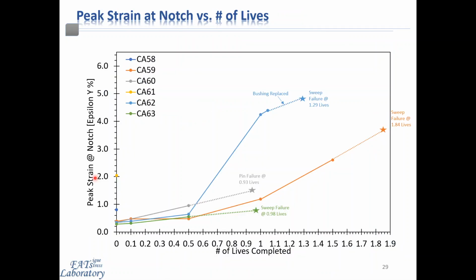So now the benefit of this technique is that we can trace and model the evolution of the peak strain in the critical region of the component as a function of the fatigue life. So the y-axis is the peak strain at the notch, and the x-axis is the number of lives that have been completed, or the fatigue life. And we can do this to understand the amount of strain required to achieve crack nucleation. So we can see that that occurs around here. So that threshold is what's achieving crack nucleation. How it affects the crack propagation rate, which is effectively the slope of this line in the middle regime, and then the nature of the final fracture, which is effectively what peak strain causes final fracture, or what peak strain can be supported prior to final fracture, of the 6 forged components which are being highlighted here.